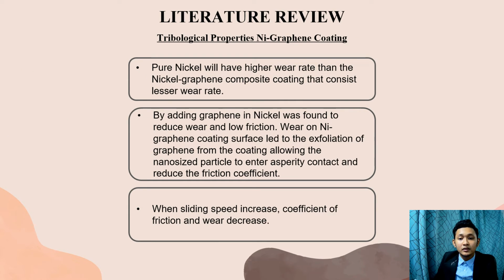Tribological properties of nickel graphene coating. Pure nickel will have a higher wear rate than the nickel graphene composite coating, which has a lower wear rate. Adding graphene to nickel was found to reduce wear and friction. Wear on the nickel graphene coating surface leads to the exfoliation of graphene from the coating, allowing the nano-sized particles to enter asperity contact and reduce the friction coefficient. When sliding speed increases, coefficient of friction and wear decrease.